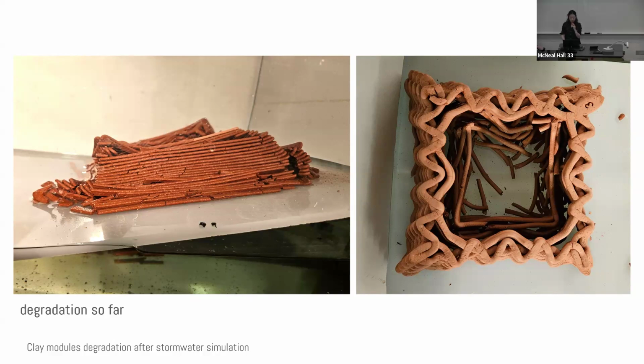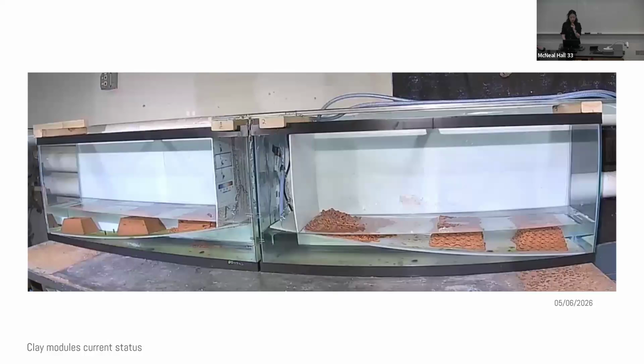An equally interesting finding was that the modules subjected to continuous wet and dry cycles, so the ones on the top, became brittle much sooner than those that remained moist the entire time. So this suggests that, at least specifically for clay materials, maintaining a certain level of moisture is critical in sustaining structural integrity. This image shows the apparatus from the trail camera taken just yesterday. You can see that the top ones, both for the wavy one and the straight one, were the most susceptible to breaking.